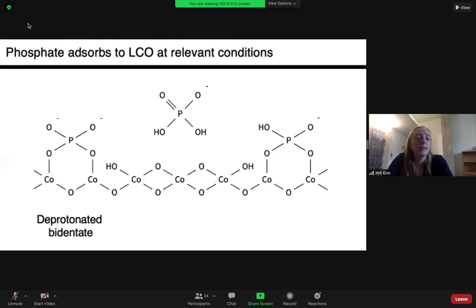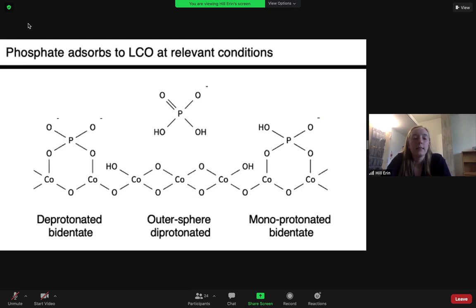The first is this deprotonated bidentate coordination. We believed that this was the most common coordination of the phosphate onto the LCO. Another coordination is the monoprotonated bidentate, and this one we thought was less common, but is evidenced by that POH bend, and so this shows that POH with the monoprotonated set of oxygens. And finally, we have this outer sphere diprotonated coordination, where we can see that the phosphate is protonated twice.